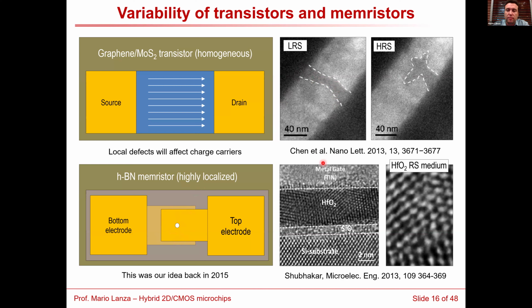Another important point is that the materials that are used for state-of-the-art memristors are bad dielectrics, which means that they contain several native defects. For example, state-of-the-art memristors use metal oxides like hafnium dioxide or tantalum oxide, and these materials are not very good dielectric materials. In fact, the good dielectric is silicon oxide grown by thermal oxidation of silicon. That is a very good material that shows a very high energy to break down, and therefore when it breaks, it does not recover. These other materials contain many defects. The dielectric breakdown takes place at lower energies, and therefore the breakdown can be recovered.